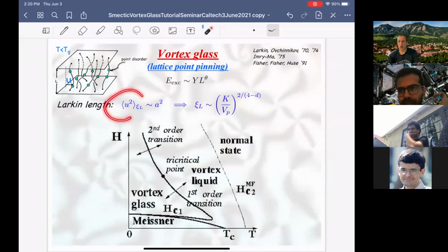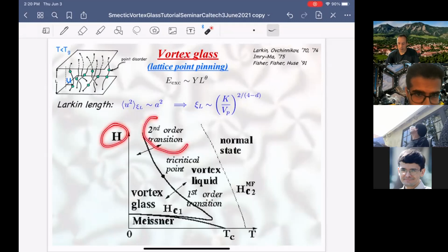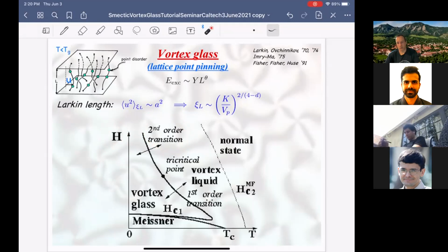Because this thing diverges with length scale, no matter how weak your disorder is, for arbitrarily weak disorder, there will always be a length scale beyond which this criterion will be satisfied. And therefore, there's always a vortex glass state that replaces the crystal. Okay, thanks for clarifying. And that vortex glass state can undergo a first order transition to a vortex liquid, at least experimentally, and also the theoretical arguments are that at high temperature or high field, it undergoes a second order transition, a melting transition of the vortex glass.